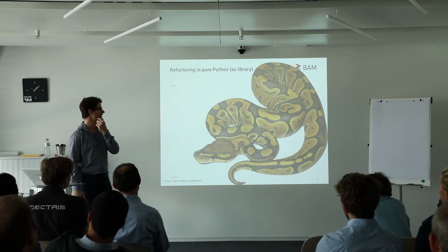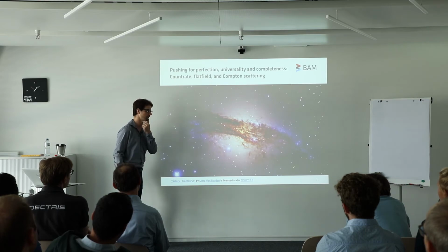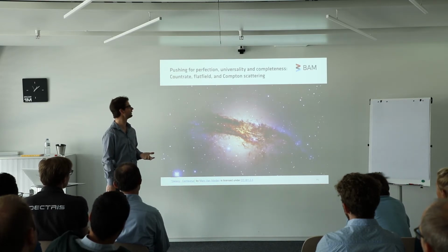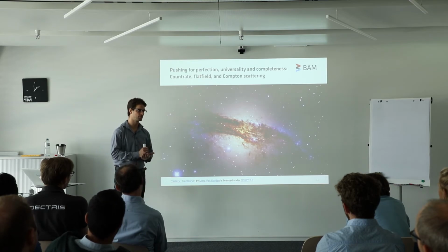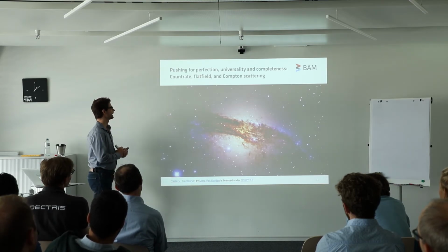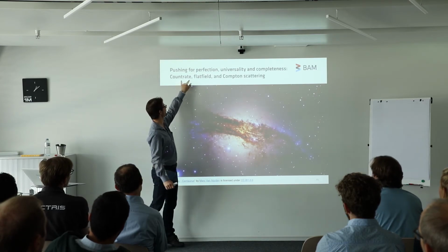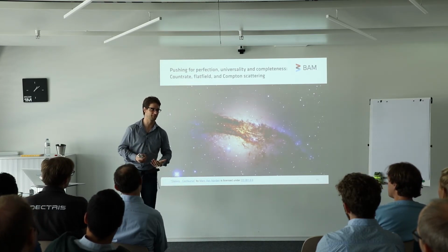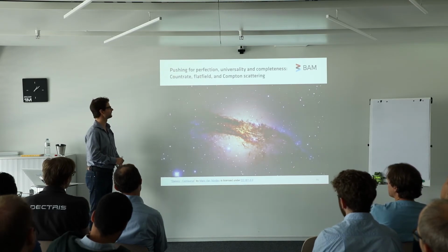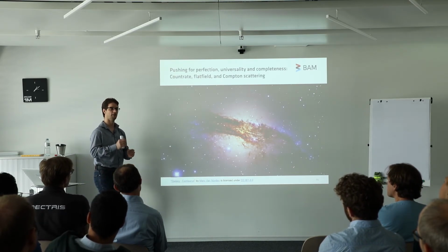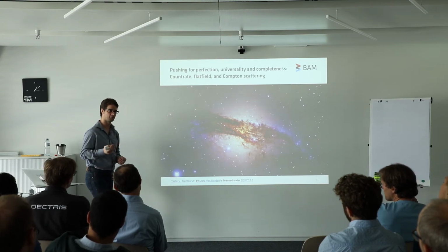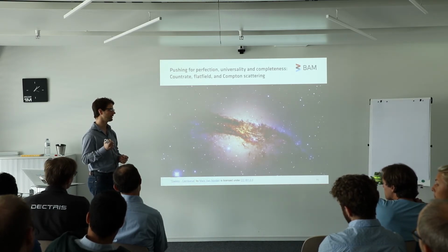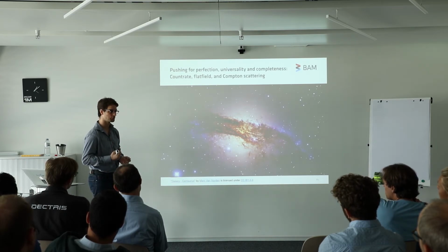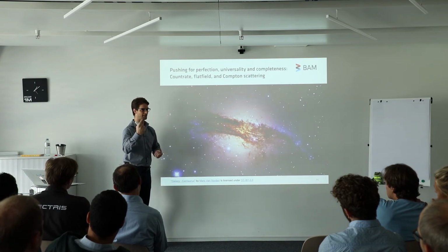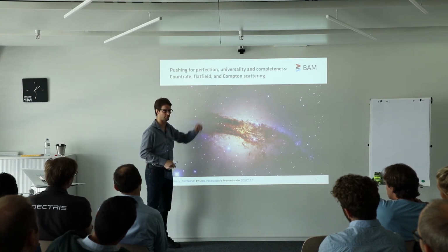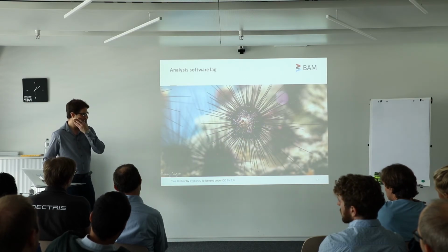Of course, our work is never done. We will still push for completeness, and for universality. I hope to include the neutron community in this as well. And there's a couple of things that we don't do yet. So count rate and flat field are still taken care of by the detector before we get our hands on the data. This is something that we want to take out, in particular because of the uncertainty estimates. The uncertainty estimates should be calculated on the actual detected photons and not on the corrected photons. So we should calculate them before we even do the count rate correction and flat field correction.